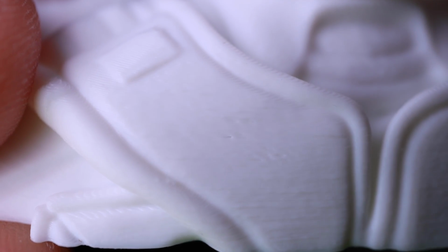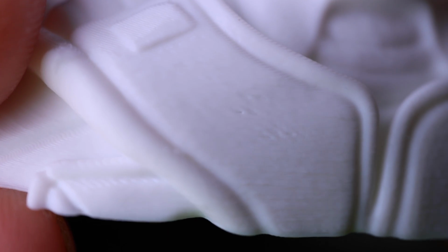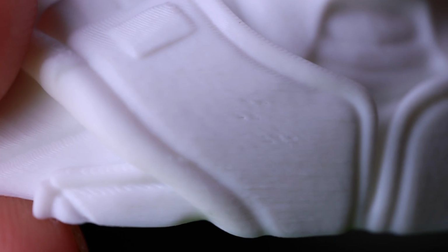Then if you look at the 160 millimeters a second speed, you can see that it has gotten even worse. This is a small model, so it's not as noticeable, but the bigger the model, the more of those issues you're going to start to see, of how it's just printing too fast and it's not keeping up with that flow. I'm just showing you multiple areas of where that's happening. You can see some bumps down here on the bottom edge. Then on the back, you can see under extrusion, and that is where the little hole is in the middle of that strap and some of those little pits, because it's constantly trying to push out enough, but it's just not going fast enough. And this is all because the nozzle cannot keep up with the speed of flow it needs.